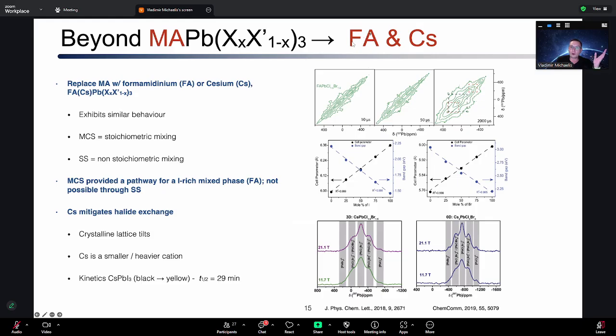What you see for formamidinium and methylammonium is fairly rapid exchange of the halogens in that system, and they're fairly mobile. It changes, though, when you go to cesium. The idea is that with cesium, the unit cell compresses itself and the lead halide octahedra tilt. We believe this compression and tilting lock the halogens in place, and you don't see any halogen exchange occurring in the cesium-based systems. So that's a unique feature of the all-inorganic species.